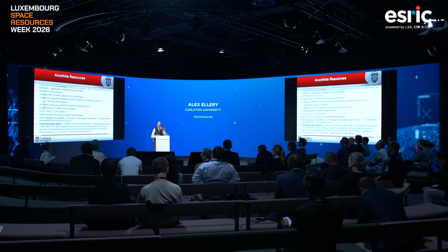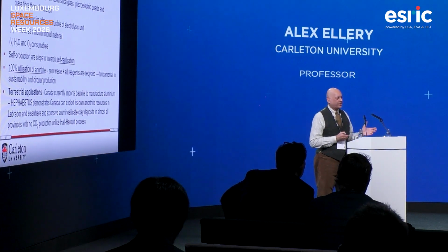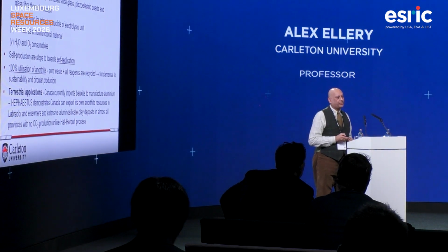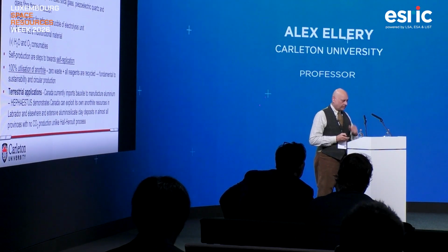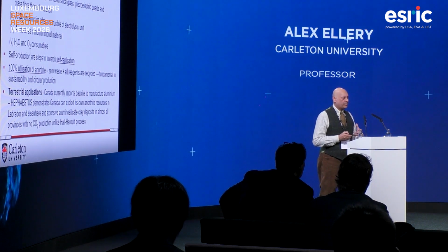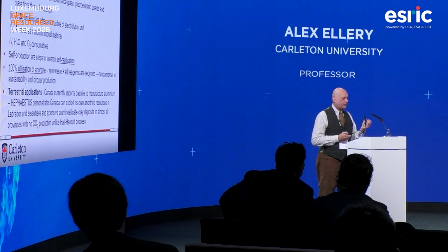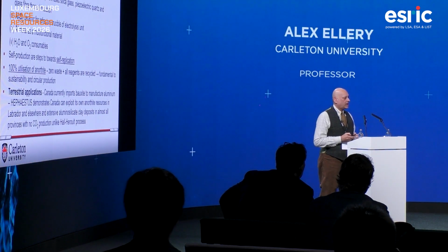Many of you will be aware that everyone and his dog has been working on ilmenite processing. We've decided to focus on anorthite, which is obviously from the highlands. What we want to demonstrate is that we can take anorthite after we've pre-processed it, and extract 100% of the material. The products we get are calcium chloride salt, which feeds essentially into the molten salt electrolyte.